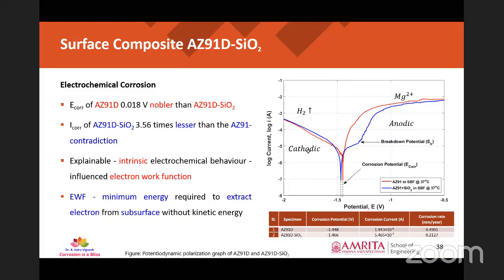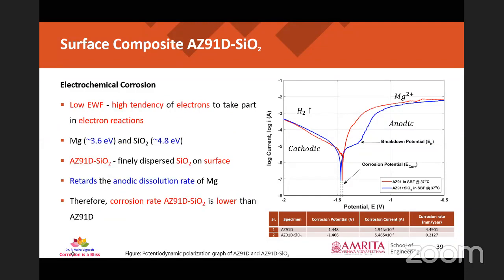So when we observe the surface potential of magnesium and silica, generally, based on the literature data, magnesium has an electron work function of 3.6 electron volt, and silica has an electron work function of 4.8 electron volt approximately. So when we have a low EWF, there is a high tendency of electrons to take part in chemical reactions. But in the case of the AZ91D silica composite, we have finely dispersed silica on the surface. So this retards the anodic dissolution rate of magnesium. Therefore, the corrosion rate of the AZ91D silica composite is lower than that of the base material.